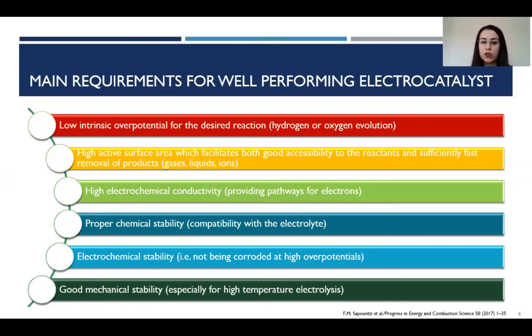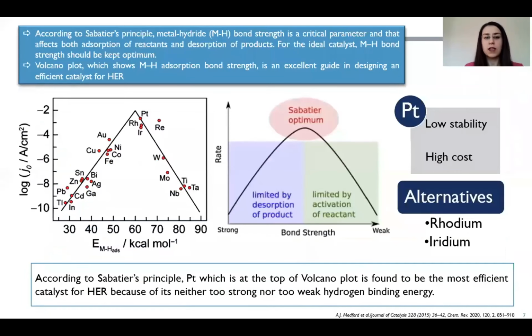Another one is the high electrical conductivity, which provides pathways for electrons. Proper chemical stability is important for the compatibility with the electrolyte. Electrochemical stability, such as not being corroded at high overpotentials, and the last requirement, good mechanical stability, especially for high temperature electrolysis. When designing an electrocatalyst towards the hydrogen evolution reaction, metal-hydrogen bond strength is a critical parameter which affects